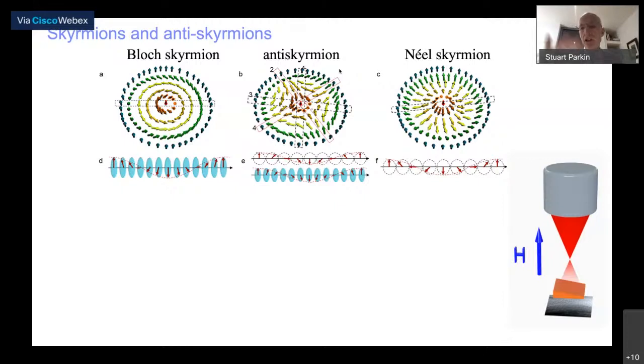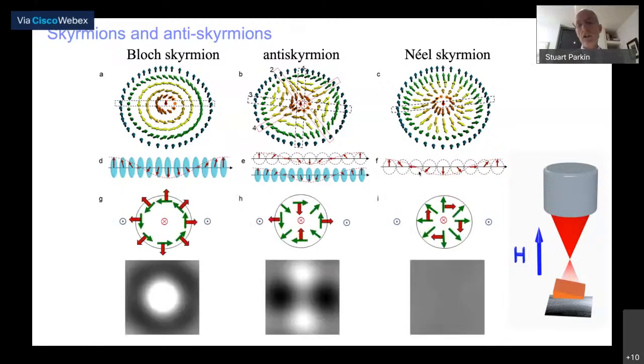And then the electrons, as they pass through this lamella, are deflected by the in-plane components of the magnetization due to the Lorentz force on the electrons. And this causes then an image to be formed that reflects the magnetic moments within these structures. So we can simulate these structures using micromagnetic simulations, and then we can calculate what we expect the pattern in the transmission electron microscope to look like.